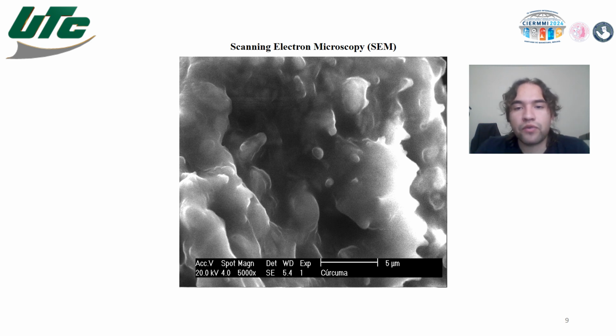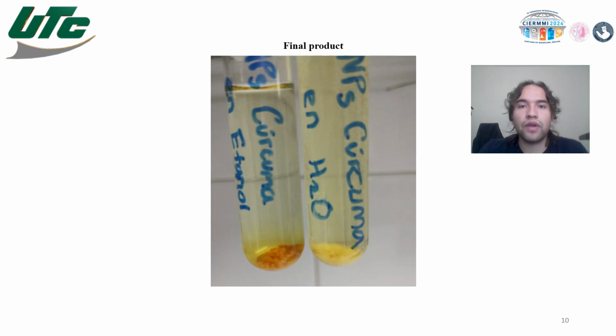The SEM micrographs were recorded at 5,000 magnifications. According to SEM analysis, the particles exhibit a semi-spherical morphology, which is consistent with the findings reported in the scientific literature. Consequently, it is inferred that the particle size corresponds to the nanometric scale. Well, here is our final product. The samples exhibit a characteristic yellow coloration in solution containing turmeric nanoparticles, consistent with what is reported by scientific literature. Additionally, a particle agglomeration is observed at the bottom of the container, suggesting the need for further optimization of the synthesis methodology to enhance the nanoparticles' stability.